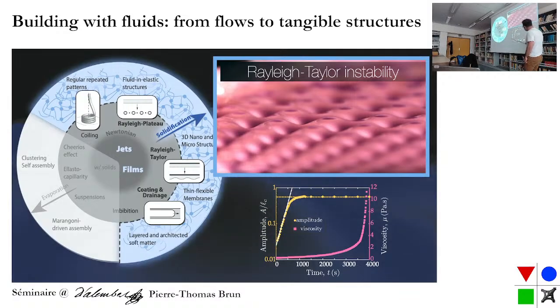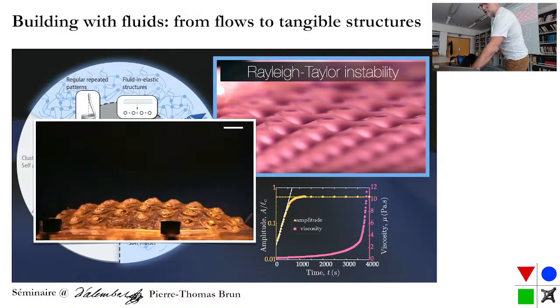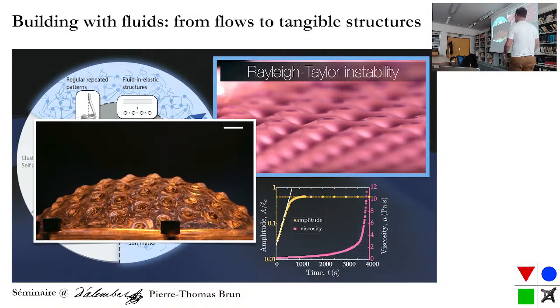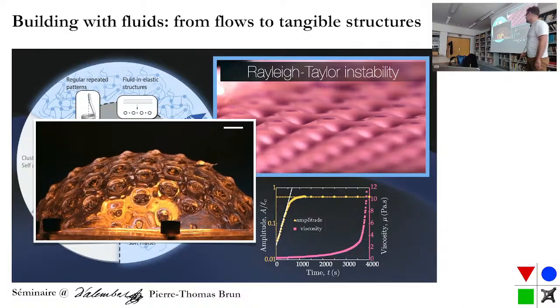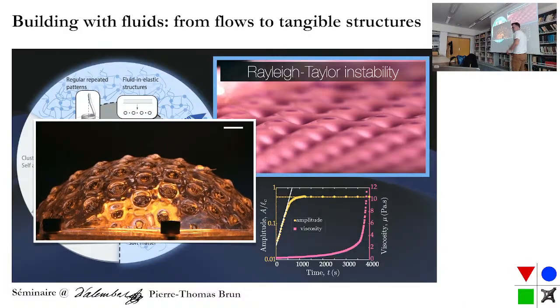And then these droplets, this is a log line, right? So they have an exponential growth, and then when they're lacking material, they sort of saturate, and their size becomes constant over time, and eventually things are cured. And because they're cured, you can do things like inflating these things. Don't ask me why, but you can inflate them just to show that they're elastic.